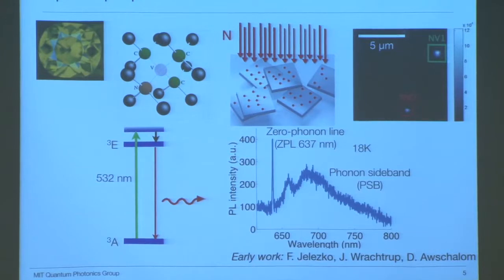And the figure on the top right corner is a scanning confocal intensity plot of a diamond sample. This sample was implanted with 10 to the 9th nitrogen atoms per square centimeter. After annealing, we are able to see these sparsely distributed NV centers. These will be confirmed to be single photon emitters, which eventually contribute to a spin-photon interface between NV and photons.